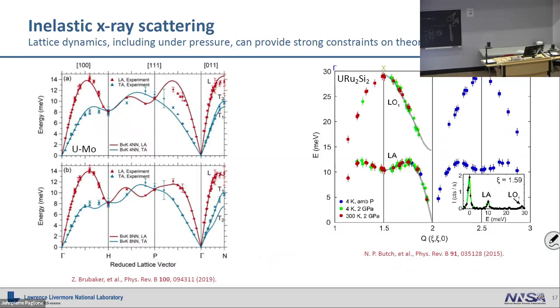The answers you get out of this, you can see a couple of things. This is a measurement that was done on a uranium molybdenum alloy at pressure, and you can pull out a lot of the answers that you want for a phonon spectra. In this case, they agree very well with a theoretical model that we had calculated. And again, for things that are like high Z materials, they scatter very nicely. You need to be thin enough that 20 kilovolts gets through it, but these are doable things.